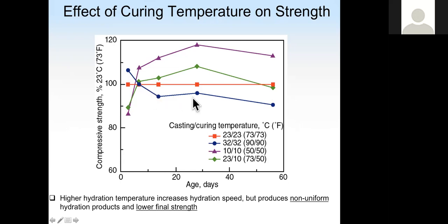The blue line is we cure at 32 degrees Celsius, and also cast at the same temperature. Okay. So compared with control mix, the concrete cured and cast at higher temperature will have higher early age strengths, but lower later age strengths. When we reduce the curing and casting temperature, such as this green line and this purple line, the early age strengths will be lower, but later age strengths will catch up.